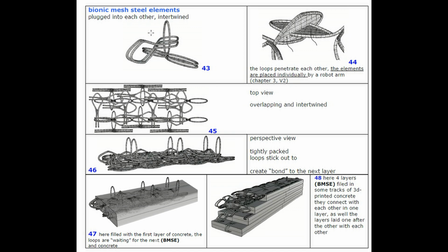You can see these elements fall into each other and the loops penetrate into the other one. Looks in the top view, they are overlapping and intertwined. The perspective view shows you they are tightly packed and the loops stick out to create a bond to the next layer. Here's one layer which is just hardened and the other one came on top. And these loops will help to connect both layers.